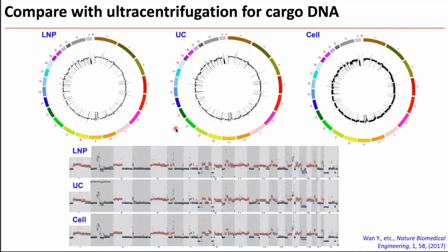So when we tested the DNA content, we found it very interesting. In this case, we studied the copy number variation of the DNA content after the lipid nanoparticle isolation. We compared that with ultracentrifugation and also the genomic cellular DNA. So what you can see from this result is that basically we don't see any difference between those three approaches from these three materials. So basically what that means is if we assay the DNA content of the vesicles, it actually can represent the DNA content of the cell where these vesicles are derived.